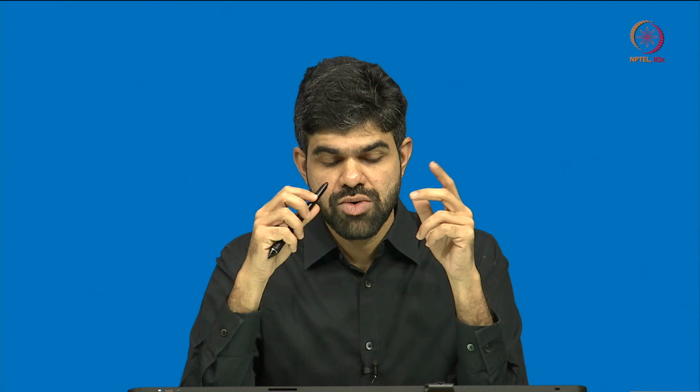So, we said in a triclinic system the only symmetry that one can think of is 1 and 1 bar. So, it can just have an identity or an inversion, and having an identity or inversion does not impose any restrictions on the axes of the unit cell. As a result, we ended up deriving that A not equal to B not equal to C, and alpha not equal to beta not equal to gamma not equal to 90 degrees, right. So, these constraints just come from underlying symmetry.